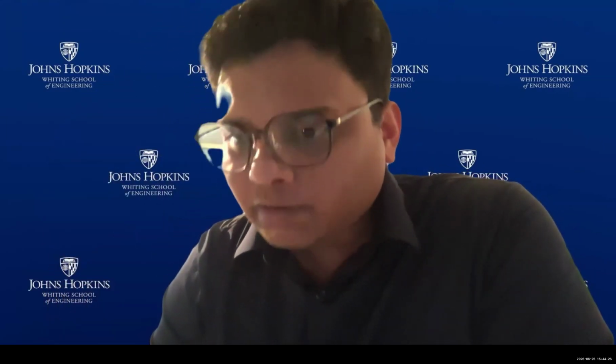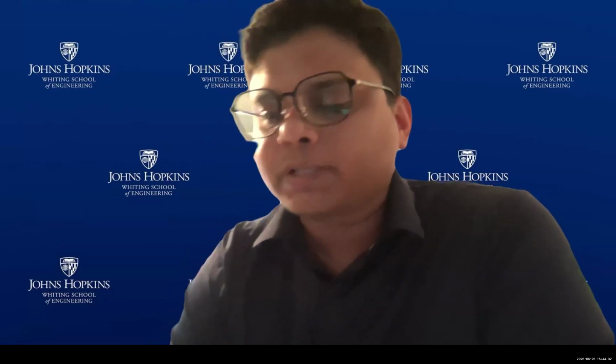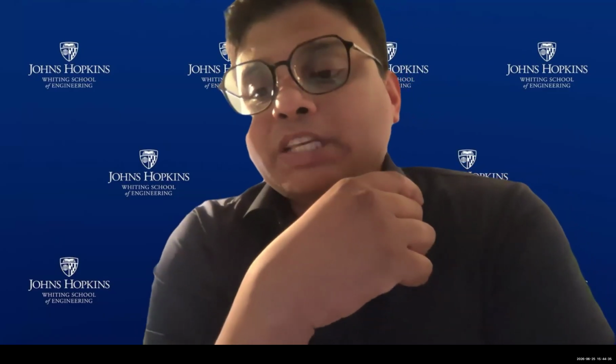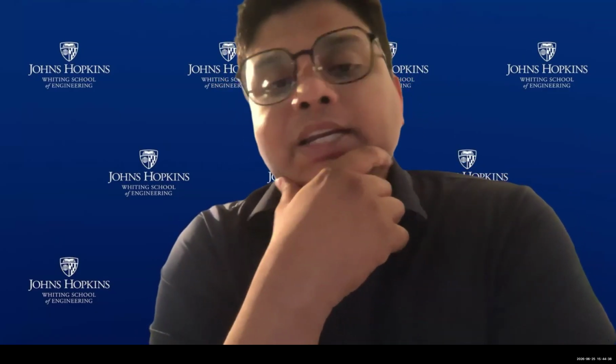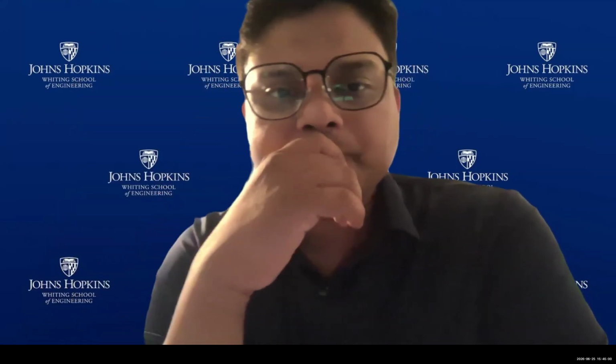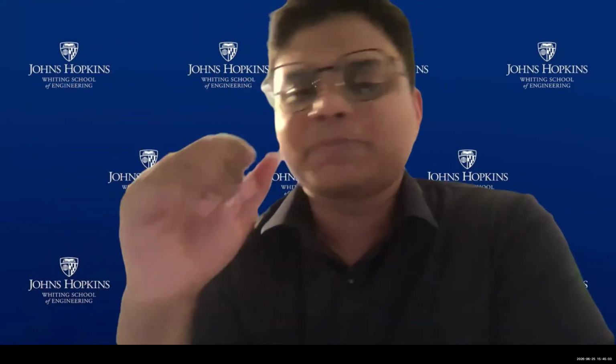We commonly think that a projected STEM image is not enough to predict the full structure. I wonder how Microscopy GPT covered the Z information not embedded in the image? That's very interesting. This was an assumption that the GPT model can do it, and this is why we did the test on 2D materials. I forgot to mention, we primarily tested Microscopy GPT on the 2D material data set of JARVIS, not 3D. For 2D, it did a reasonable job, and I believe it can be extended to 3D as well, like the full Z depth. So it's still a proof of concept kind of idea.